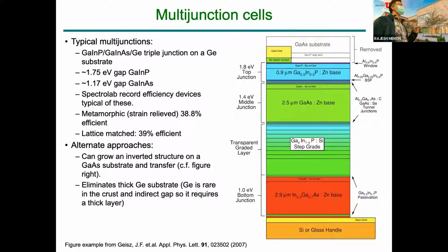The other reason why you need a transition region here is because the lattice structure of this material may not match the lattice structure of this material. So two different crystal lattices, you cannot grow one on top of each other. There will be too many defects. Defects are bad because that's where the electrons and holes get trapped. And that's the efficiency loss for the system. So these are very important technological reasons why this has been done with what's called epitaxial growth, where you draw one layer of atoms at a time. Very complicated system.